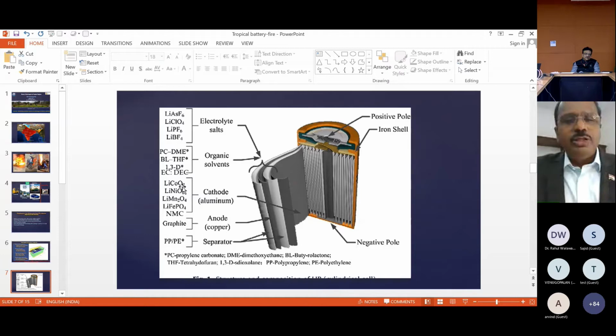So this is one of the reasons NMC is not good if you don't have proper electronics. Otherwise, I don't mind driving an NMC car like Tesla. And then there is lithium iron phosphate, LiFePO4. You use only iron for low cost, which is relevant for India, but you don't have cobalt, and you have phosphate, PO4, and the phosphate network is so strong covalently that it doesn't allow the oxygen to escape. That means the flash point or firing temperature is much higher than NMC, at least 70 to 80 degrees centigrade above, it doesn't fire, it doesn't release oxygen. And the graphite is in the anode part, which is carbon.